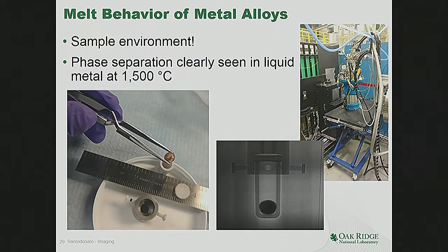So we are actually imaging, we're heating these materials up. This shows us loading into a ceramic cell. A little pellet goes in the cell, we load it up. That's a raw radiograph. So there it is inside this furnace. It's hanging in there, waiting to be heated. I didn't have time to add a lot of stuff, but we were seeing in real time. This is one of the reasons why we stayed at the instrument so long, because it's fun. We start to heat it up, and you can tell this is before it's melted. The pellet doesn't have exactly the shape of that container, but over time, when we were looking at these slices last night, you can see that ball just kind of collapse and take the shape of the container.